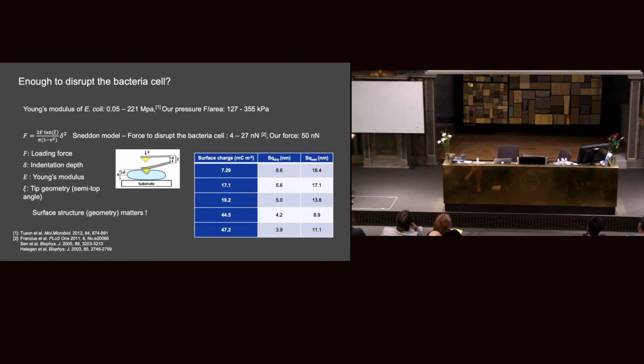So it means that if our force is 50 nanonewton, and if we have, for example, a sharp enough surface or structures, it is possible to break the bacteria. But it's hard to decide which is the reason for our antibacterial surfaces. One thing we are sure is that the surface structure really matters.